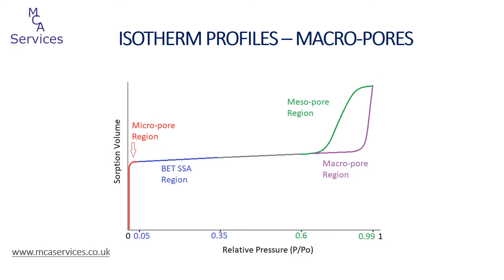An alternative isotherm profile will be observed for macroporous materials. As these have pores larger than mesoporous material, the increase in adsorption volume due to their filling commences at a higher relative pressure. Once pores become too large, they won't be completely filled with adsorbate as saturation is approached — the highest relative pressure we can measure. For nitrogen adsorption at liquid nitrogen temperatures this will be close to one. Consequently, we observe an adsorption isotherm profile without a Gurvitch plateau but instead an asymptotic increase in adsorption volume.